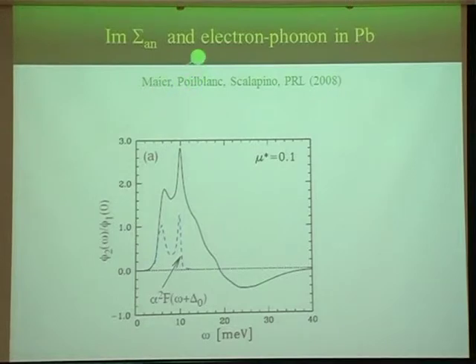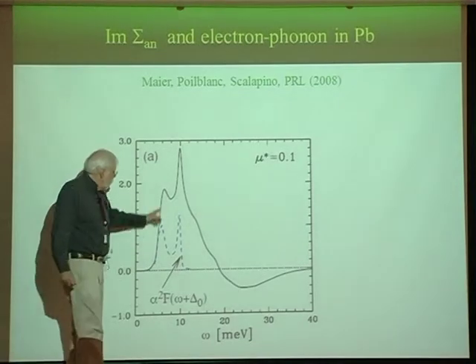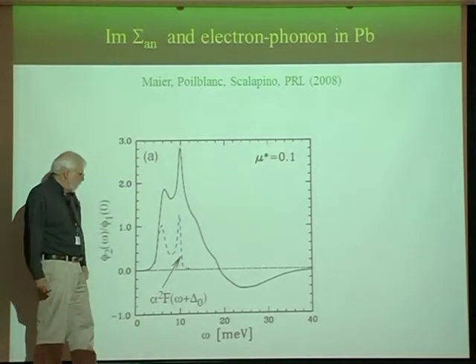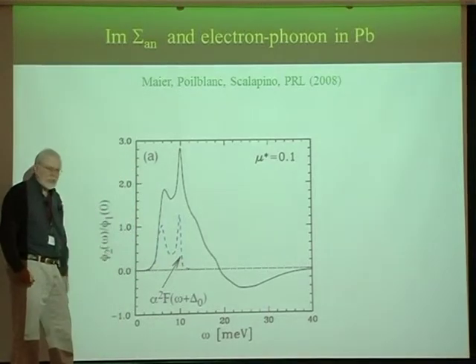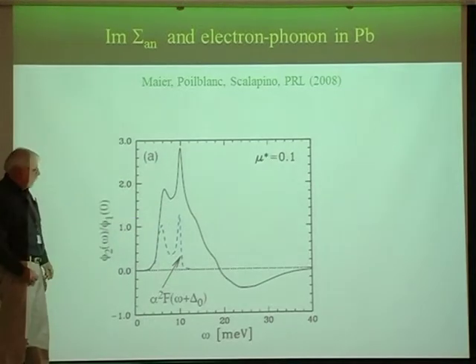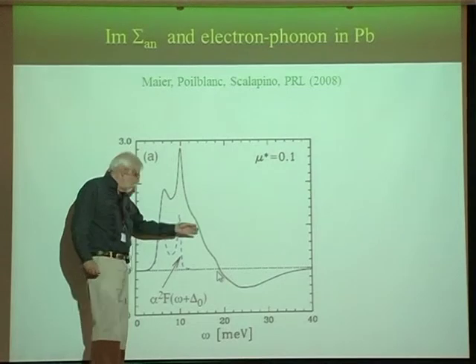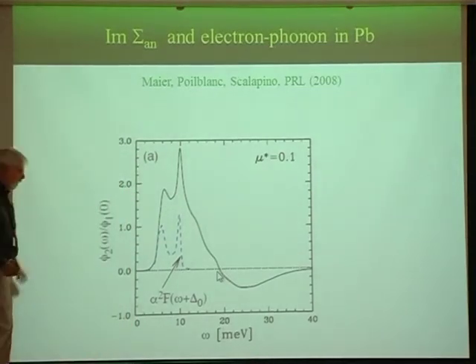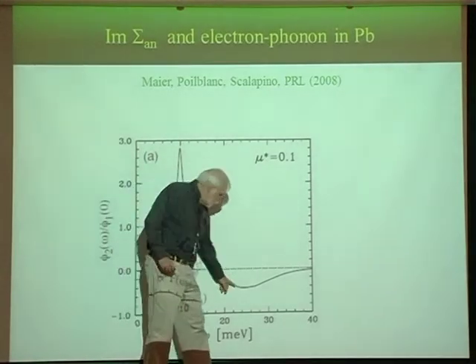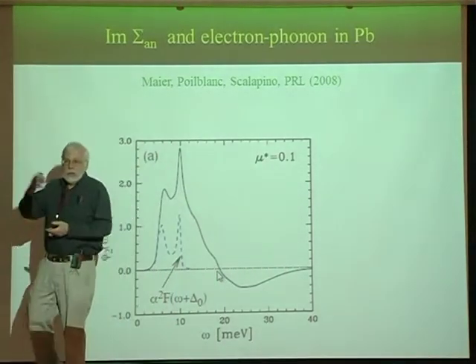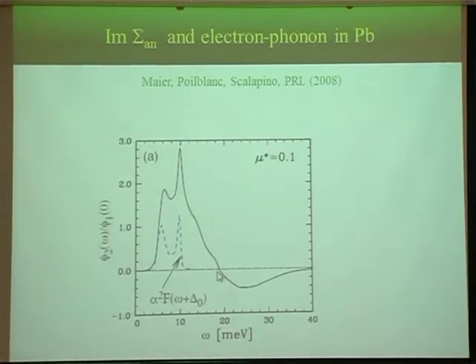So let's go back to just ordinary electron-phonon interactions in lead. What is plotted here, taken from this paper, is the imaginary part of the anomalous self-energy, the off-diagonal self-energy, as a function of frequency. You can extract this from tunneling curves. And you see that these two peaks here are the same as those that you see in the phonon spectrum measured by neutron scattering. If you just shift by the gap, you see that these coincide. And you see replicas of these here that were seen experimentally and that are quite convincing arguments. The other point I want to make is that this imaginary part can become negative. It's an off-diagonal component, so causality does not restrict it to have a single sign. I will come back to the meaning of this negative part in a moment.